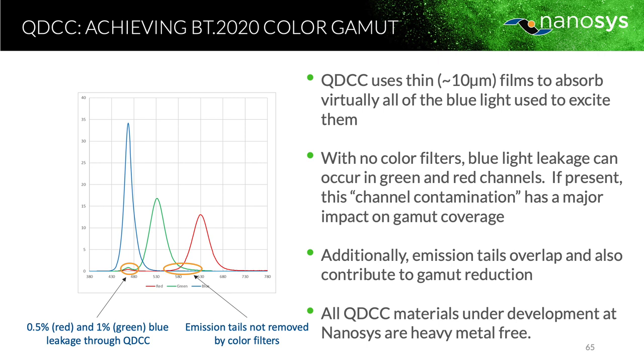So in the spectrum which comes from a display of this type, what you'd like to see is three peaks, red, green, and blue, and nothing else. And in fact, that's what you see. But if you look carefully under the blue peak, you see there's a blip from the red and the green. And so what we're seeing is about 0.5% of blue light in the red spectrum, and about 1% of blue light in the green spectrum. So why does this happen? This happens because not all of the light is absorbed by that layer.